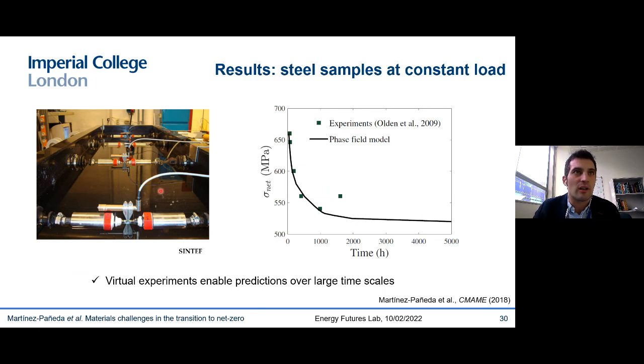And these are a set of a bit more interesting experiments. These were done at SINTEF in Norway. They have a seawater bath. They introduce some samples. They have a notch, and each of these samples is subjected to a constant load, a different load. Each sample had a different load. And they were just waiting to see when cracking will occur. Their hope is that one of the samples was charged to a load small enough that you will never see hydrogen embrittlement, you'll never see failure, because hydrogen embrittlement requires a stress.